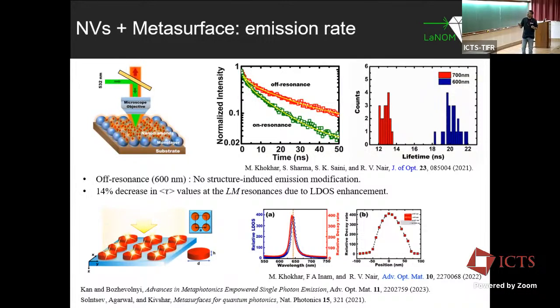And these are very simple structures with microspheres, because we don't have a lithography lab to make these high index systems. But once you have clean room facilities, you can make nice silicon or diamond cylinders, and you implant a single NV center or single emitter. Theoretically, we calculated around 400 times enhancement, and you can suppress all the phononic contributions. We published this analytical and theoretical calculation recently in Advanced Optical Materials, and it was a cover page also.